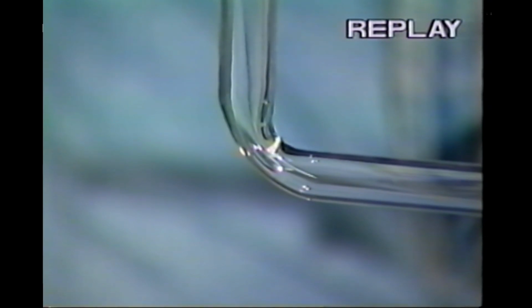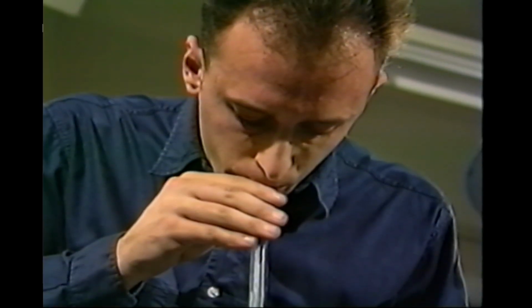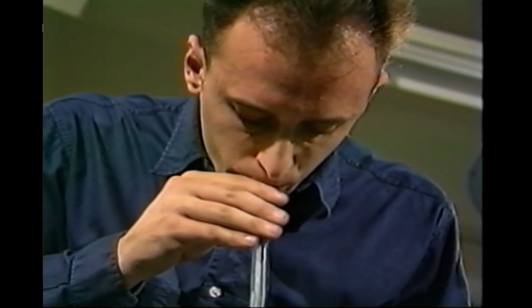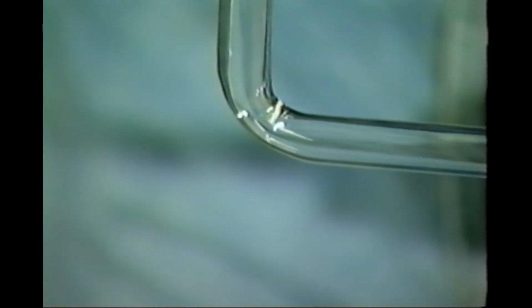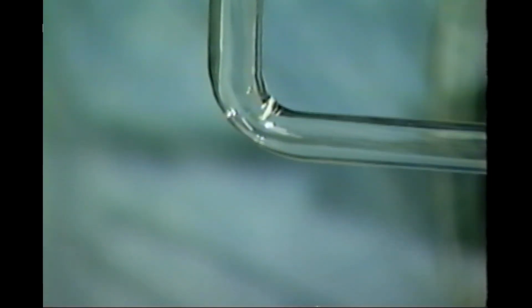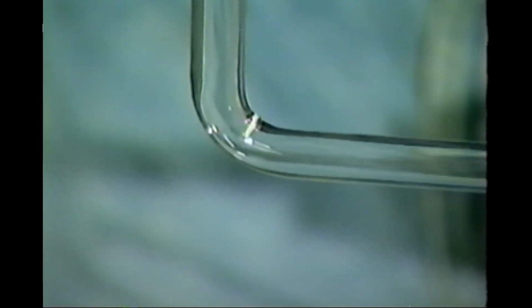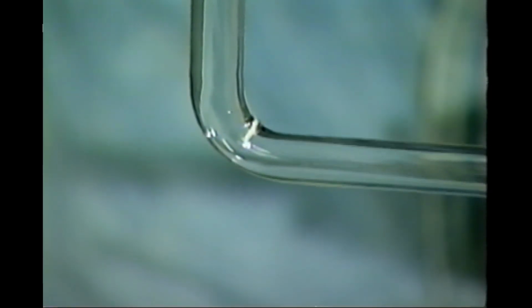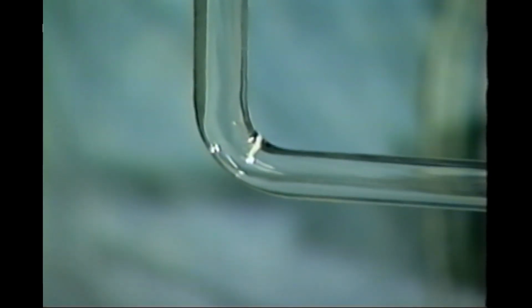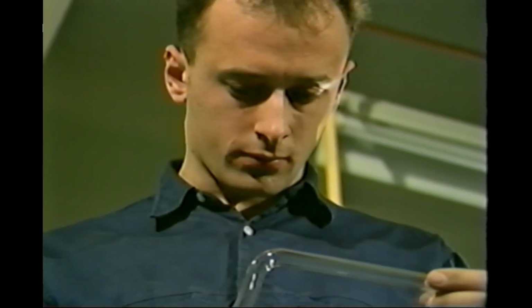When the right side has been shaped around to a vertical position, the right angle is achieved. At this point, lower the head to enable blowing to take place. Blow gently into the tube, only until the collapsed tube diameter is restored. Cease blowing and allow the tube to cool slightly before moving from its held position.